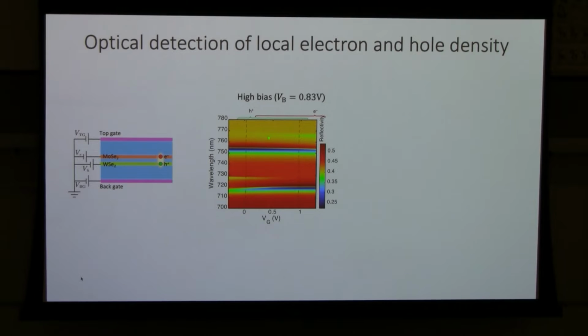For example, if you look at the top resonance coming from the MoSe2 layer, you can see the exciton feature but also the trion feature. That means there are electrons in the MoSe2 layer. The bottom part corresponds to the optical transition in the WSe2 layer. Again, you see the exciton feature and the trion feature. That means holes are also doped in this system. So you can see electrons and holes are indeed simultaneously doped.